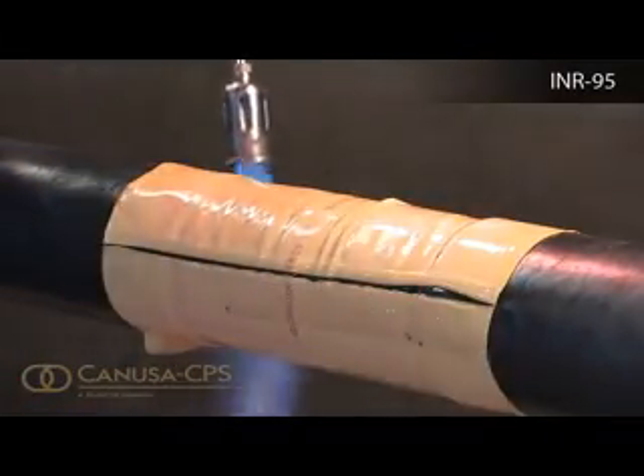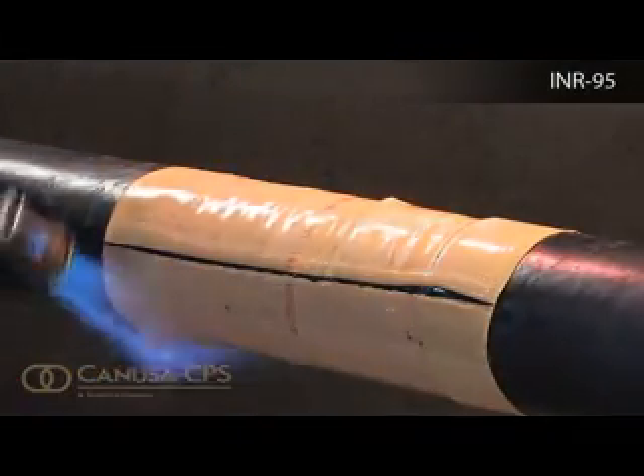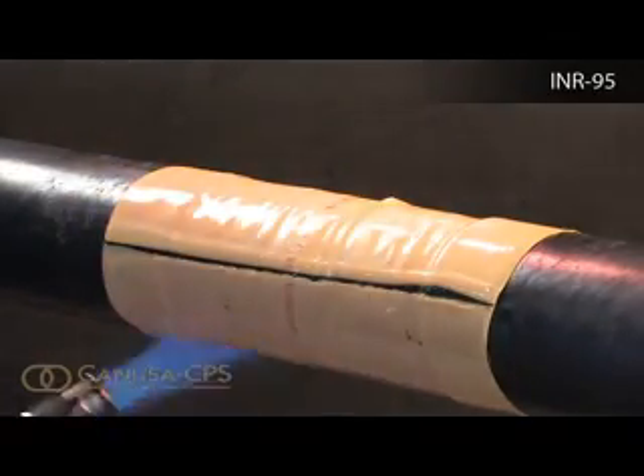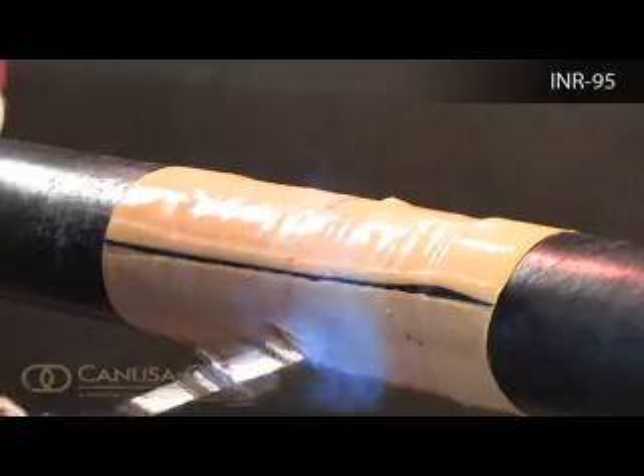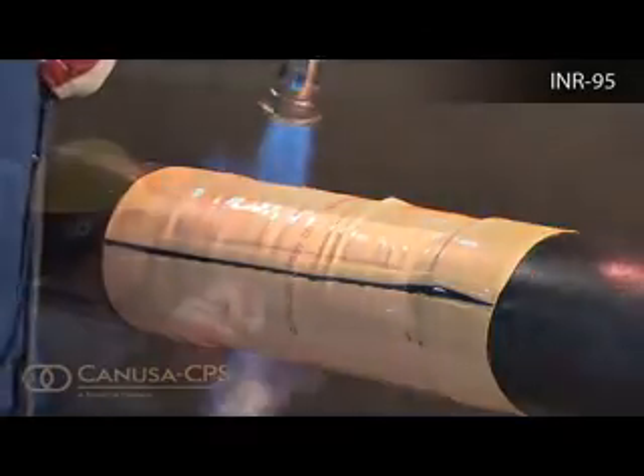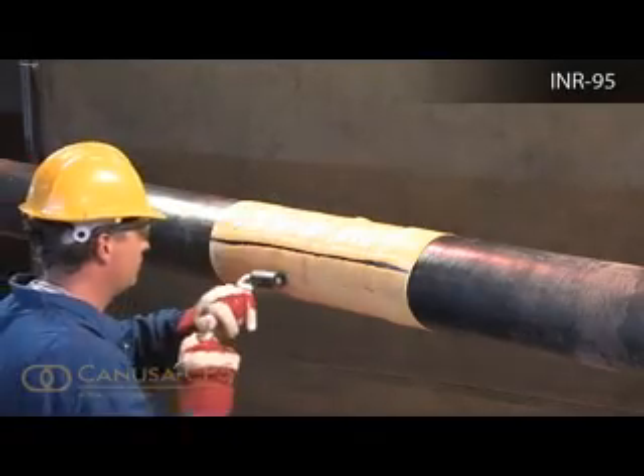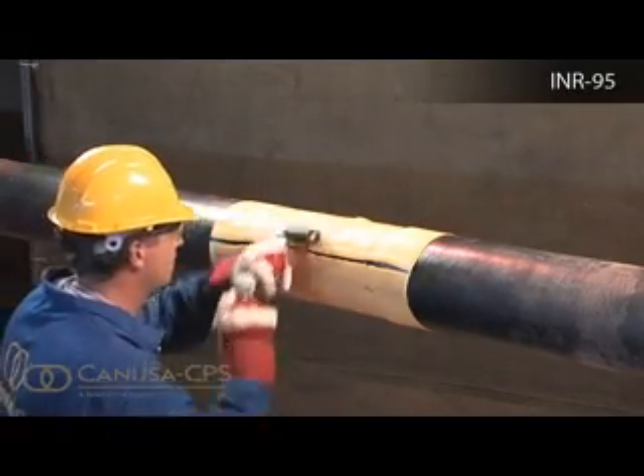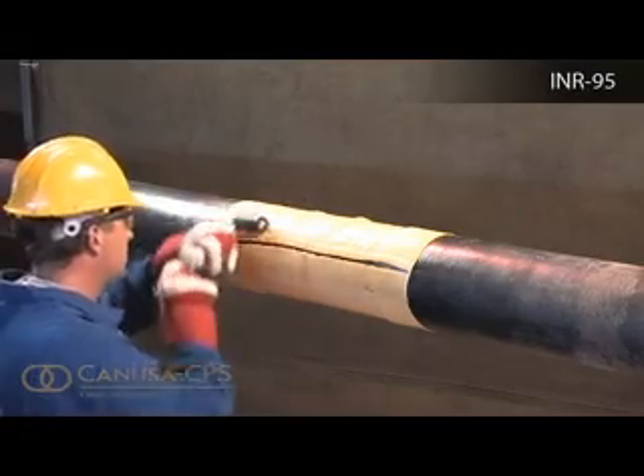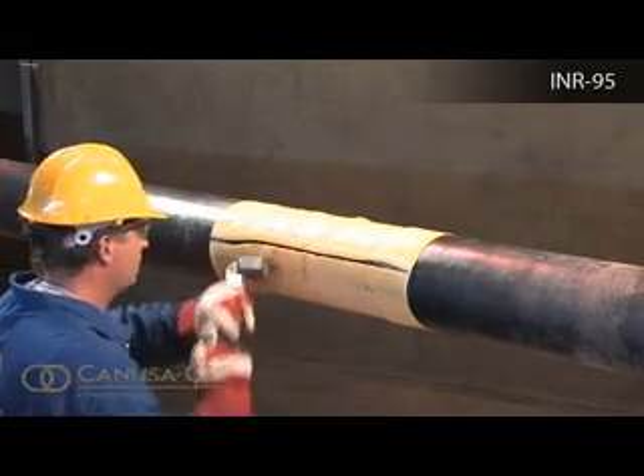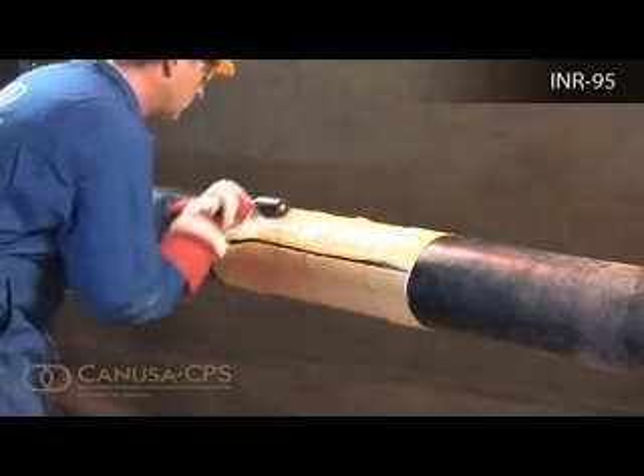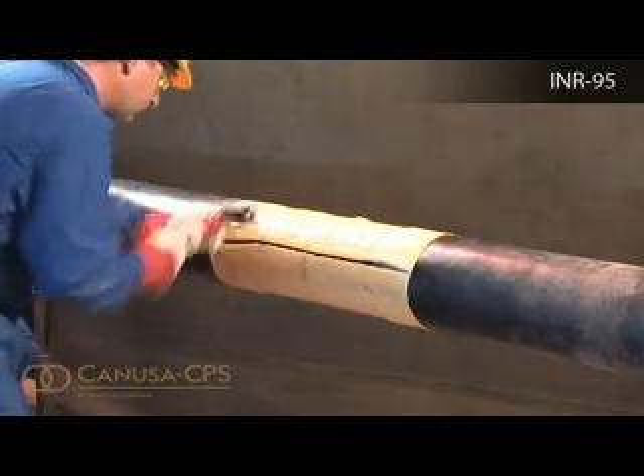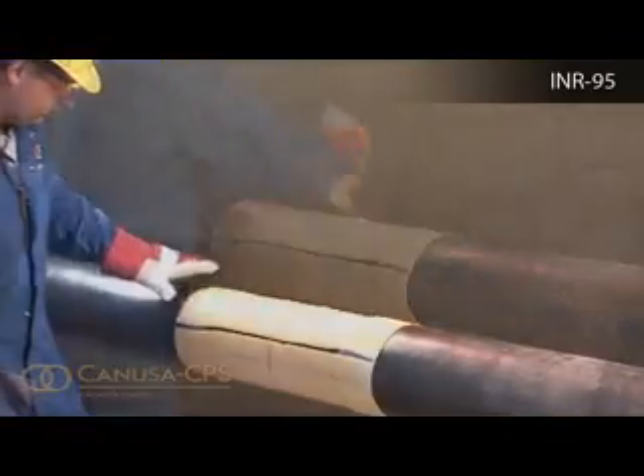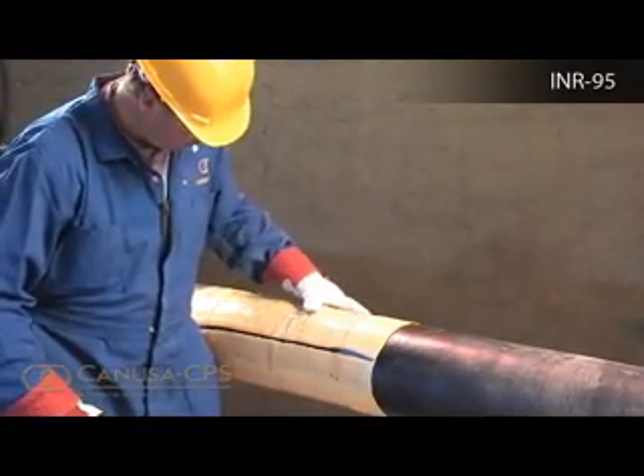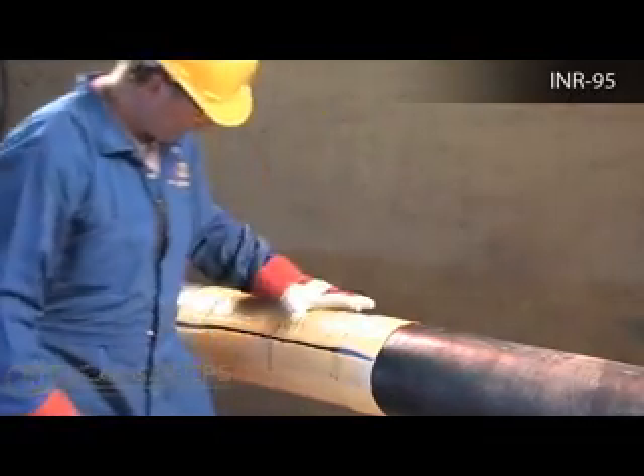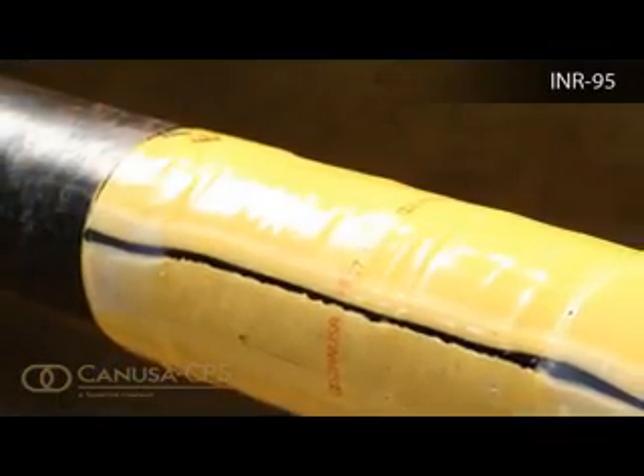Shrinking has been completed when the adhesive begins to ooze out the edges and the sleeve is in full contact with the pipe. While the sleeve is still hot and soft, use a roller to roll the sleeve surface and push any trapped air up and out of the sleeve. Visually inspect the installed sleeve and make sure that the sleeve is in full contact with the steel joint, that the adhesive flowed beyond both sleeve edges, and that no cracks or holes are in the sleeve backing. After shrinking is complete, allow the sleeve to cool prior to lowering and backfilling.